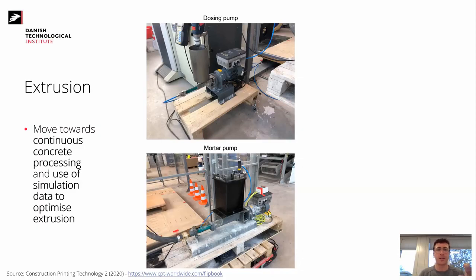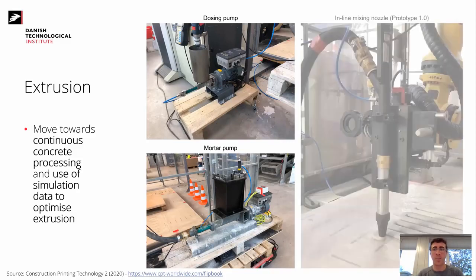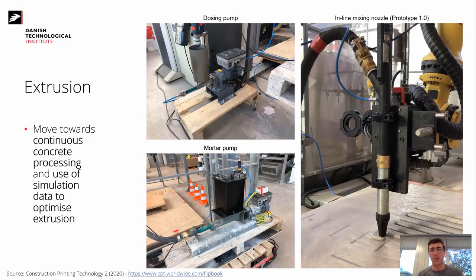So I'm just highlighting two photos of an equipment we were running with, a normal progressive cavity pump for the mortar, a similar approach for a dosing pump, injecting an accelerating ingredient to the nozzle. And then in the nozzle, we have a mixing shaft with an injection inlet where both materials meet, and within 10-15 seconds of residence time in the shaft, they are mixed and ready to go. That means we can accelerate the mix and eventually stack the layers.